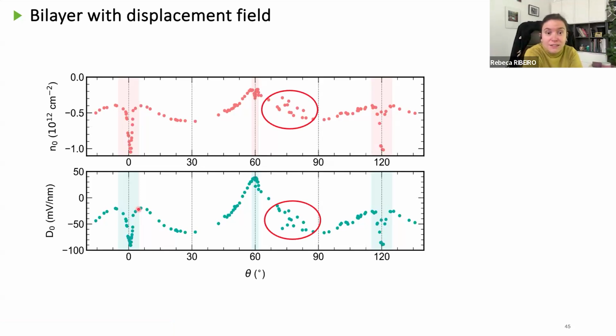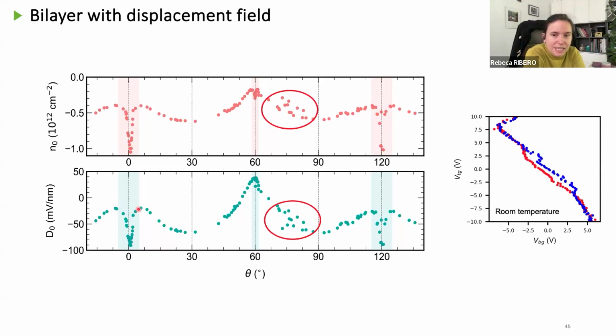So it's not a problem with our sample. It's in fact, when you are stepping there and you make a gate-gate map, you observe this. And this is a hysteretic behavior close to charge neutrality. In fact, this is the position of charge neutrality. The red dots are when the gate is swept to the right, and the blue dots are when the gate is swept to the left. So you can see that at the beginning, the points are pretty much on top of each other, and then at some point they start to have a hysteretic behavior.